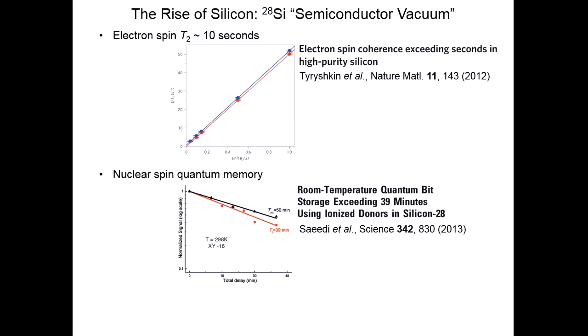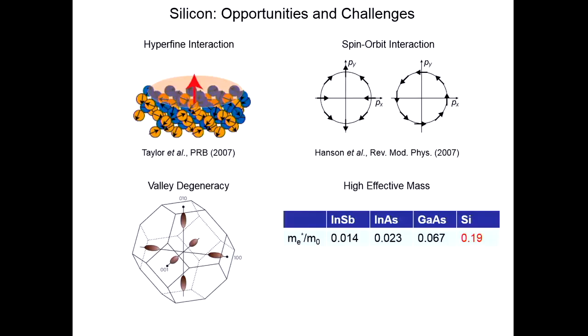All right. This is exciting, but there are a lot of challenges associated with going from, say, 10 to the 20 or 10 to the 18 spins in an electron spin resonance experiment down to just one spin and doing the same experiment with one spin. And all right, so hyperfine can be dealt with. Silicon's lighter, which means the spin orbit coupling is weaker. There are some trade-offs, and this is why single electron physics in silicon is hard.